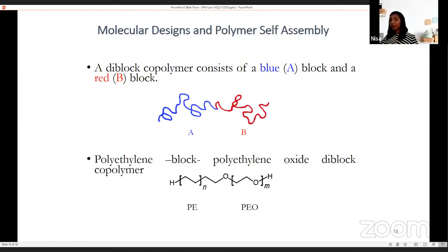at nano level. Here is a diblock polymer called polyethylene block polyethylene oxide. This is an amphiphilic block polymer where the polyethylene block is hydrophobic in nature. So when such a polymer dissolves in water, these molecules self-organize in such a way that all the hydrophobic parts form the core and the hydrophilic part forms the shell. That's the way they form sphere-like particles at the nano level, and they are called micelles.